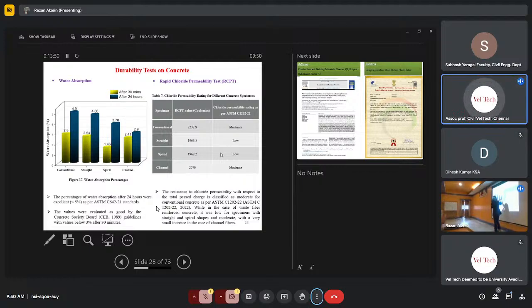We can see here that all of them have very good and excellent water absorption. However, we can see that after 30 minutes the fibers have projected the least water absorption. The least water absorption means the concrete is more durable, the concrete is more resistant to exterior chemicals. Then moving to the 24 hours, you can see that also there are good, excellent results. However, the fibers in this case are the ultimate.